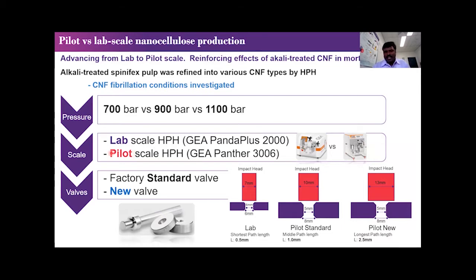We tested different processing variables, like varying the scale of the nanofiber-making HPH, the high pressure homogenizer, versus the pilot scales that we have, and also the different valves involved in the homogenizer. The different lengths all affect the fibrillation efficiency. What I mean is that when you get the pulp after the mild alkaline sodium hydroxide treatment, you get bundles of nanofibers, so you need to apply shear treatment to get the nanofiber. It looks simple, but it actually involves several variables to get well defibrillated nanofibers.